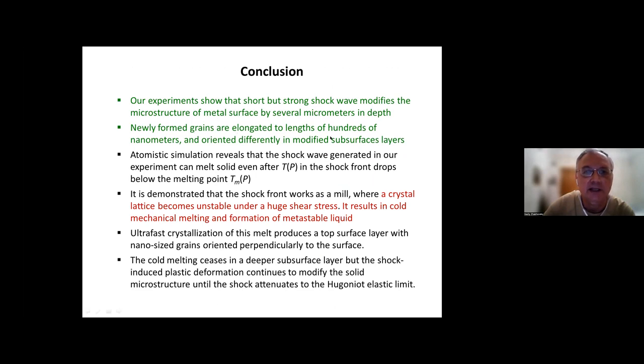Newly formed grains are elongated, hundreds of nanometers in length, and oriented differently in the modified subsurface layer. These green points indicate our experimental observation, but our simulation revealed that the shock wave generated in the experiment may melt the material, even if the temperature at the shock front is below the melting point at a given time and a given pressure.